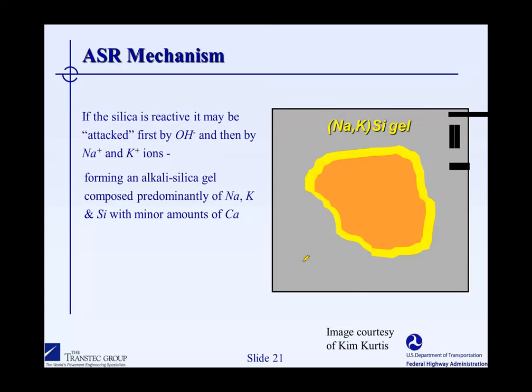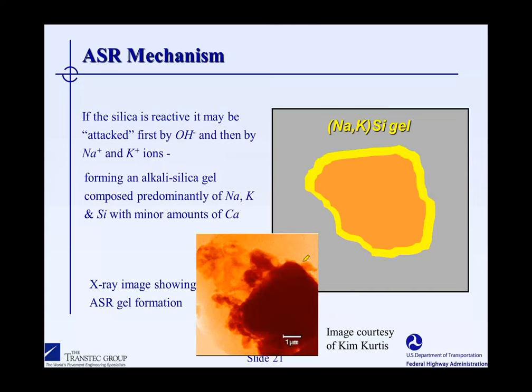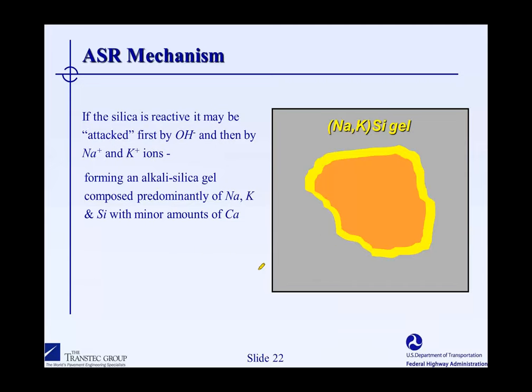Basically, what happens is the very high pH, the hydroxyl ions, break down the bonds that hold the silica together. The silica passes into solution. It dissolves, if you like, and then it combines with the sodium and potassium in the solution to start to form a gel-like material, what we call an alkali silica gel. This X-ray image here from Kim Curtis of Georgia Tech shows a reactive silica particle passing into solution. You can get a sense of the solid material dissolving into a high alkali solution. That's initially what happens in the high pH in the concrete. The silica that passes into solution will combine with sodium and potassium and with minor amounts of calcium that's available too, and form an alkali silica gel.